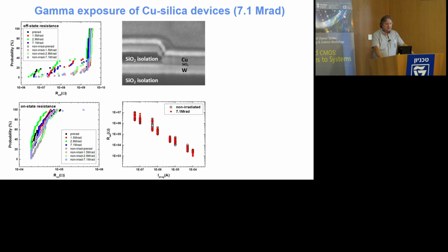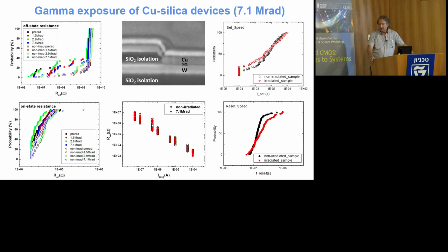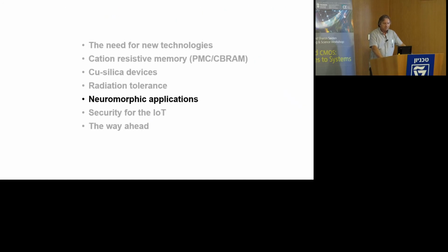And looking at performance, resistance, the ability to program to different resistance states, and the general off-state and on-state behavior of the devices, there's very little change even after 7.1. In fact, we've taken them up to 10 megarads gamma in these, and we got pretty much the same results, which is very impressive. These things are hard to kill.